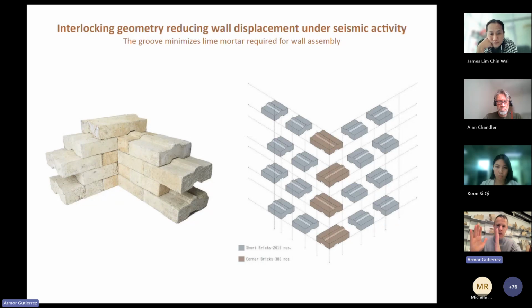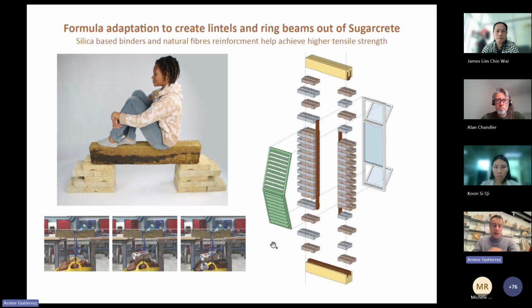and how, if you were within a module that is set by the size of these blocks plus the mortar that is required to put them together, you would avoid any cutting of blocks when it comes to windows, openings, or lintels. We developed a lintel prototype as well, changing slightly the formula so we could create something that had good resistance on a 3-point load testing, which we did here in a bit of a homemade way, just adding a weight in the center.